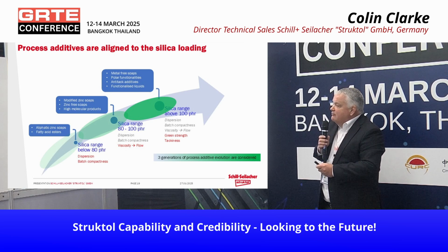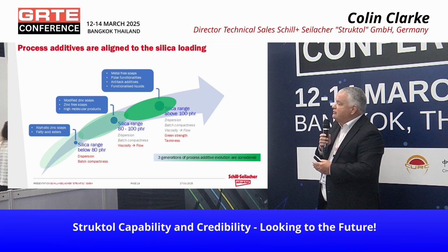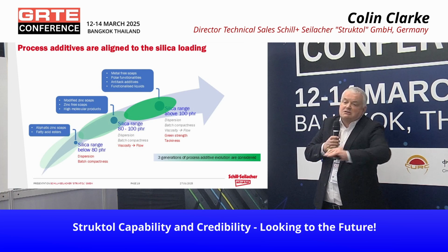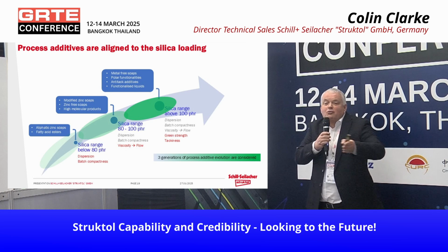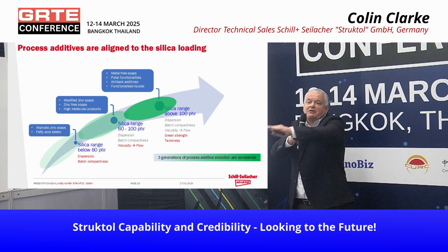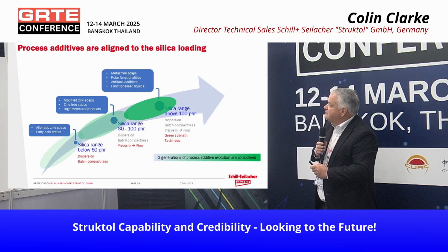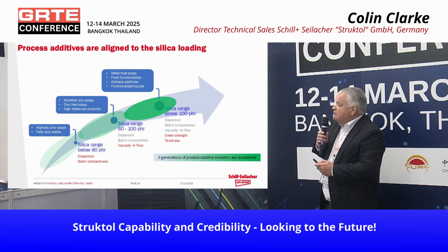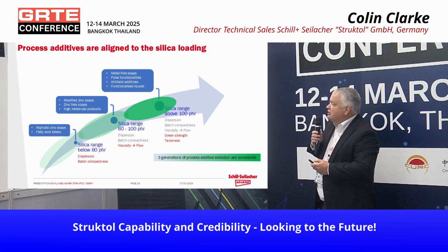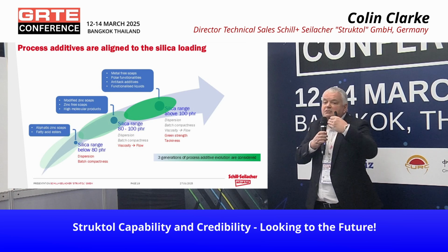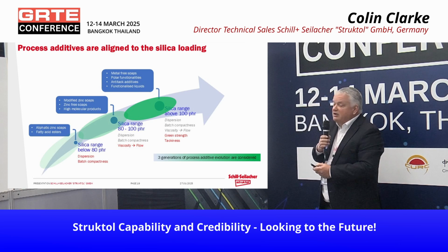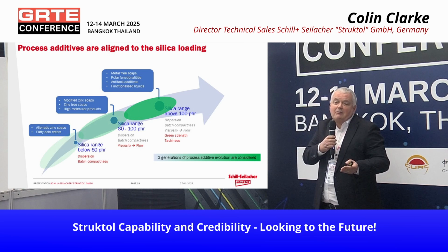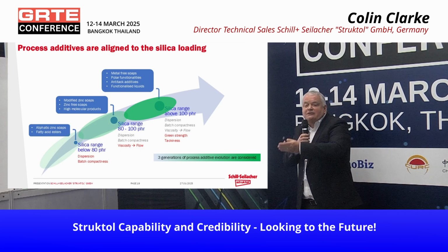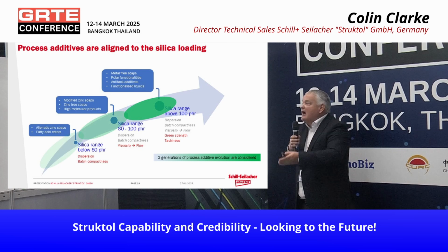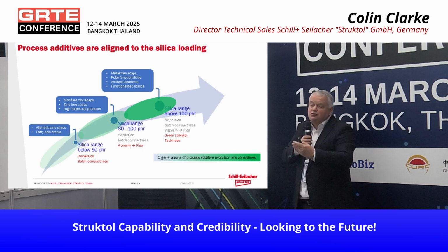Actually, we can track the development of tread compounds, particularly passenger compounds, to the increase in silica loading. So 20 years ago, silica was not a thing. Today, more and more silica is used in passenger tyres, starting in Europe and now spreading really globally. If we say initially, we had silica at a really very low level and we had very standard zinc soap products in use. Later on, silica increased and we needed to modify those products to be more active towards the silica. And today, actually, in passenger tyres, certainly in Europe, there's more silica than polymer. More than 100 parts of silica, maybe up to 150 parts of silica. The challenges change, and so the additives must also change to be much more active towards the silica.